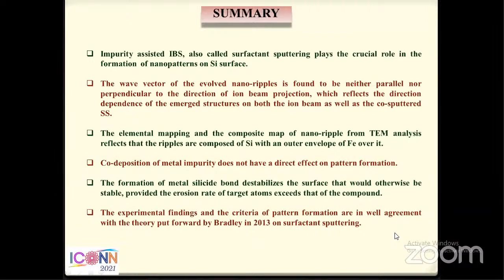So these are my conclusions. Here we can say that surfactant material plays a very crucial role in the formation of nanopatterns on silicon surfaces. And also the direction of the ripples that evolve on the surface depends on both the direction of the ion beam as well as the co-sputtered material. Also, the co-deposition of metal impurity doesn't have a direct impact on pattern formation, but the formation of the silicide bond plays the main role.